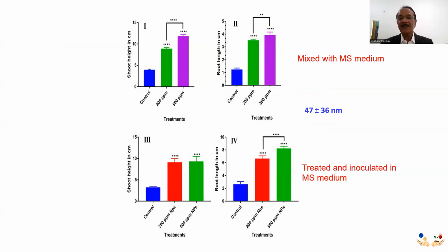And then the nanoparticles were mixed in the Murashige and Skoog medium, and then maize seeds were grown. Murashige and Skoog medium is a medium which is used in plant tissue culture for growing the seeds or plant organs and tissues. And in other experiments, we treated the seeds first and then inoculated them into the medium. In both experiments, we found that 500 ppm of nanoparticles is much more effective.